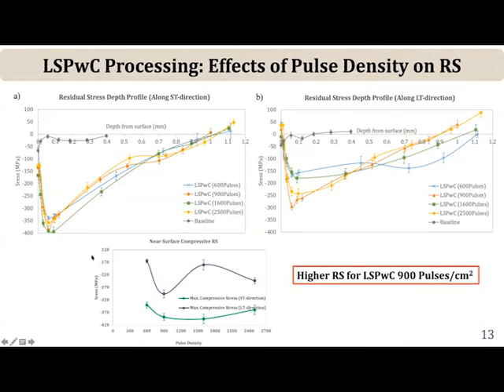So this shows you essentially when you do the laser peening without coating, this is along two directions, the short transverse direction and along the LT direction, two orthogonal directions, the measurement. So you can see that the baseline material is slightly compressive on the surface, but relatively low residual stresses. And one important thing, as I mentioned, is initially Anurag looked at the impact of pulse density. And you see here the surface stress as a function of pulse density is shown. And what he found was that at about 900 pulses per square centimeter, you get some optimal levels of compressive residual stresses in both the directions. So essentially for subsequent studies, chose this 900 pulses.